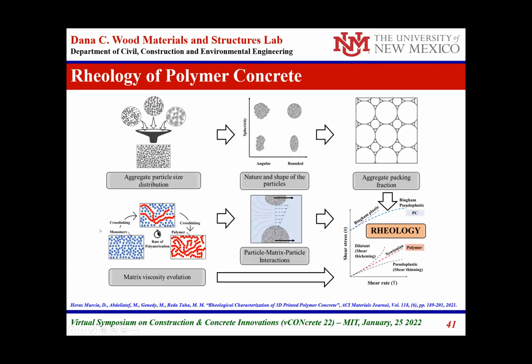So we started using the polymer concrete and some of the modified nanomaterials to 3D print it. To do this, the only difference from the cement concrete case is that here the matrix is a polymer. In these polymer concretes, by the way, there is no cement at all—we are replacing the cement completely with a polymer.